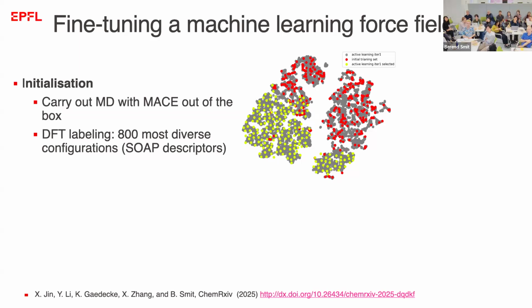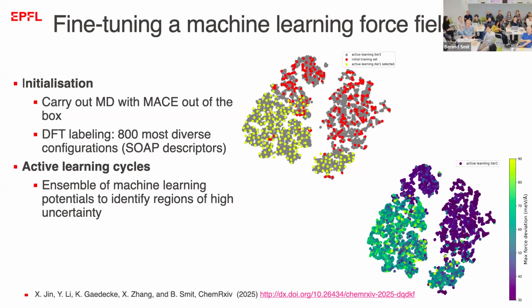Then what you do is those active learning rounds. So you continue your molecular dynamics simulation, but now we have 4 different machine learning models. You train them with different random numbers. So you have a measure of the accuracy. So if the 4 machine learning force fields disagree a lot, then you say, okay, it's not sufficiently accurate. We need more training data in this region. And that is illustrated here. This part are configurations that have a high accuracy, and in this part the accuracy is poor, and you see that. And then we again use the same idea.